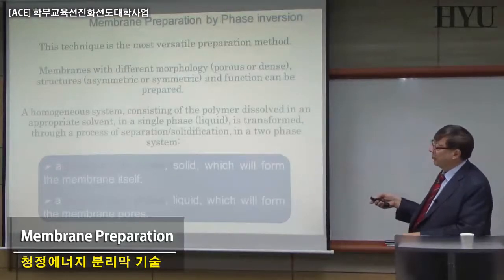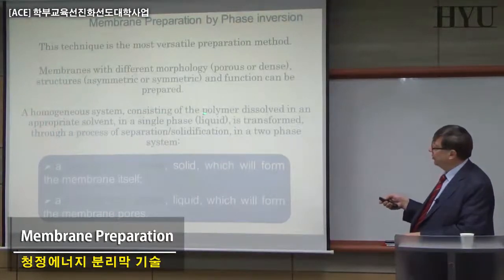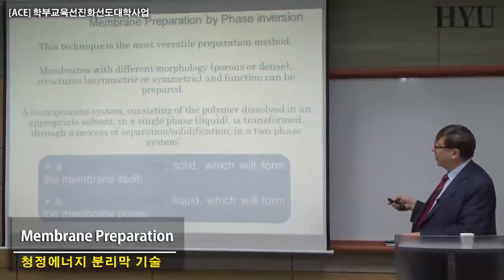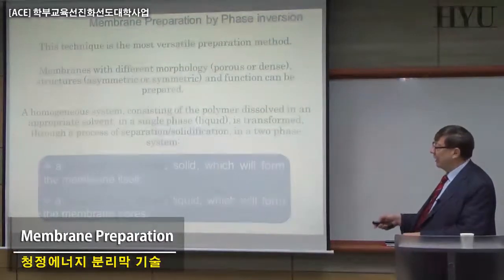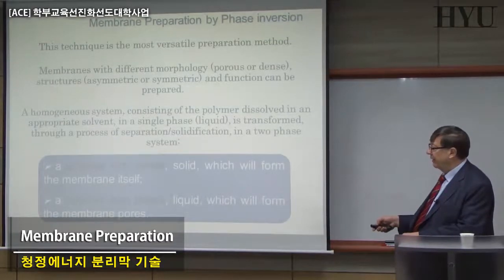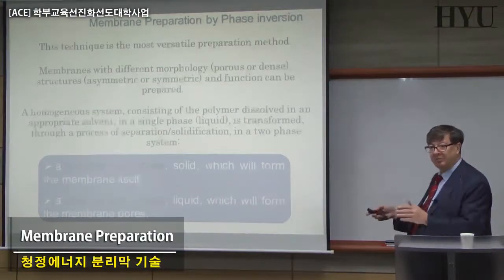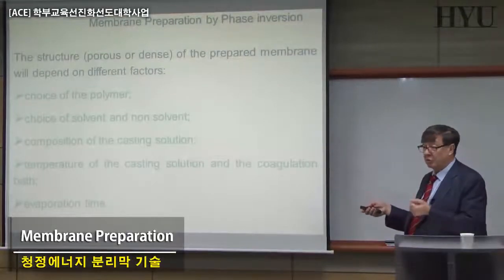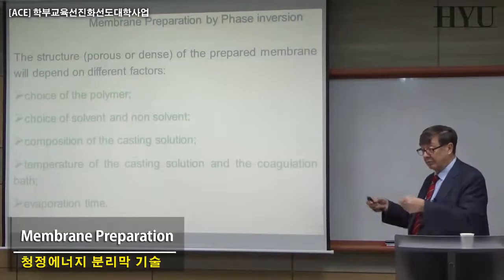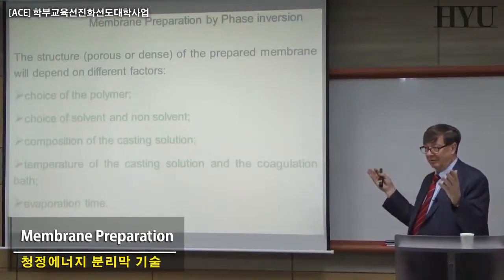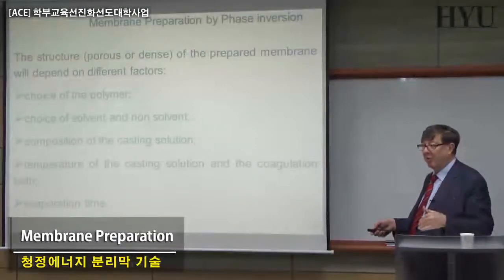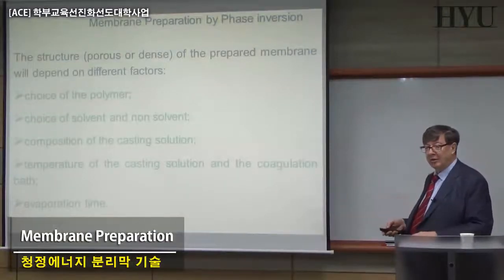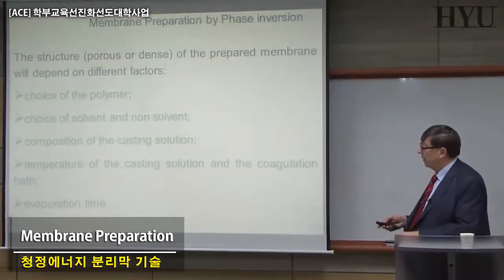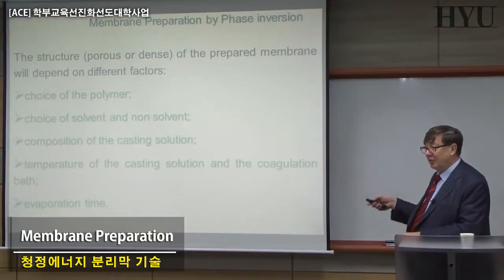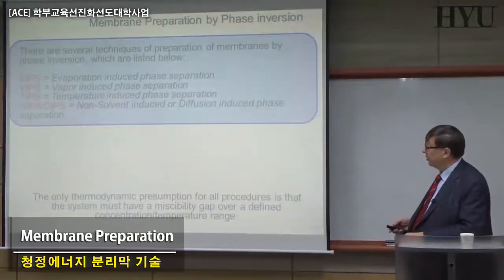But anyway, this is the most traditional system: a homogeneous system consisting of the polymer dissolved in an appropriate solvent, a single-phase liquid, is transformed through a process of separation and solidification into a two-phase system. A polymer-rich phase, solid, which is the membrane, and a polymer-lean phase, liquid, which will form the membrane pores. This is basically the mechanism we are considering. The choice of polymer, solvent, non-solvent, composition, concentration of the solution, temperature of the coagulation bath, the evaporation time where you freeze the process, are all parameters that can significantly change the final properties of your membranes. And today this is no more an art. Now people know how each of these parameters changes the final property of your system.